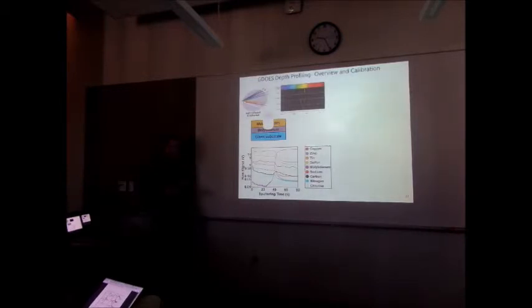So GDOES is a depth profiling technique where you light a plasma over a sample and you sputter away the material. This material diffuses into the plasma and emits light, which you can diffract and collect, and you have these little portions of the rainbow here. Each of these portions of the rainbow are a fingerprint for each of the different elements, basically. And this gives you some elemental signal as a function of sputtering time. So this is uncalibrated data. These are arbitrarily scaled due to how complicated plasma physics is.